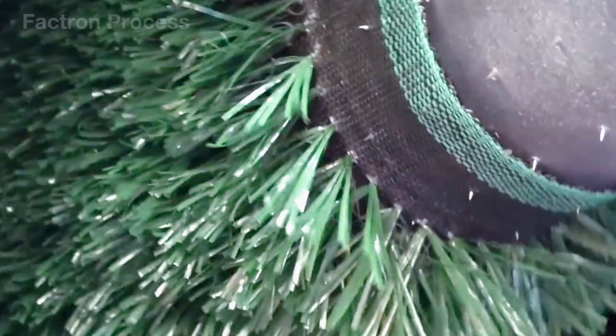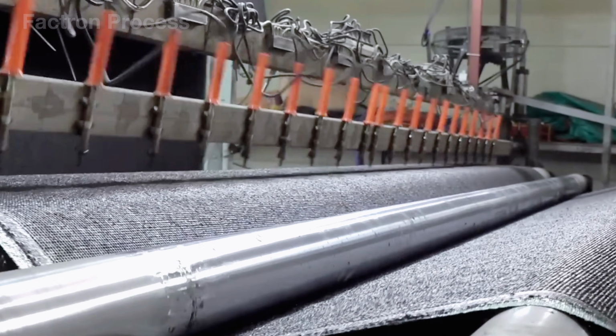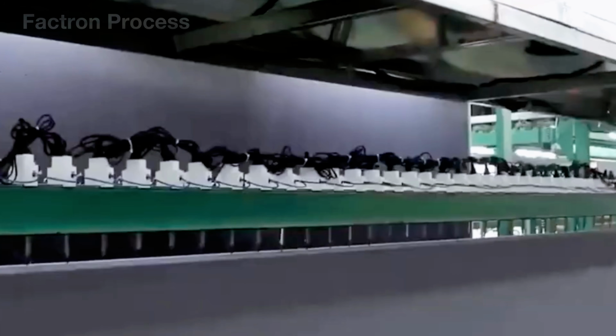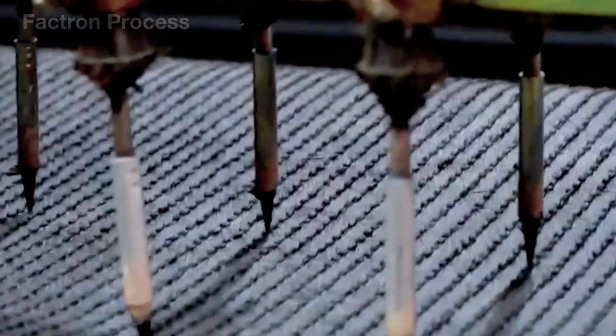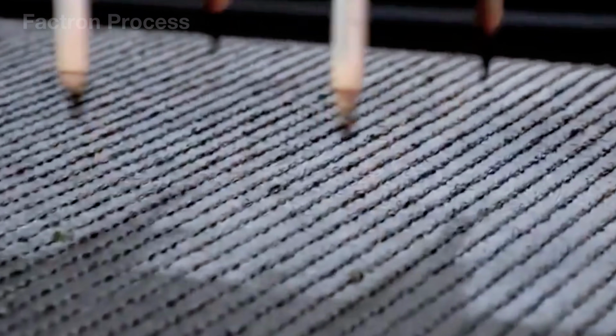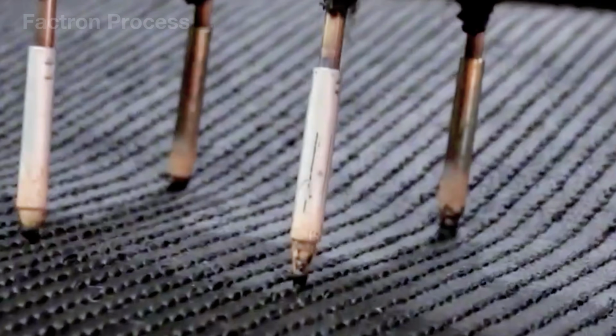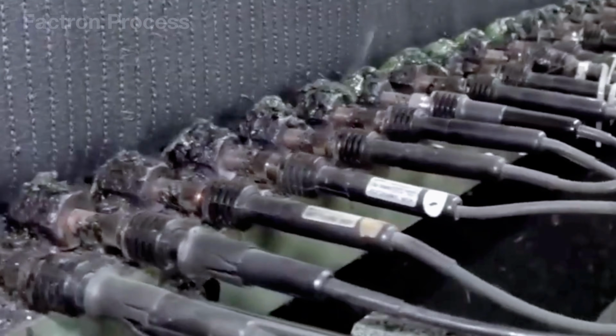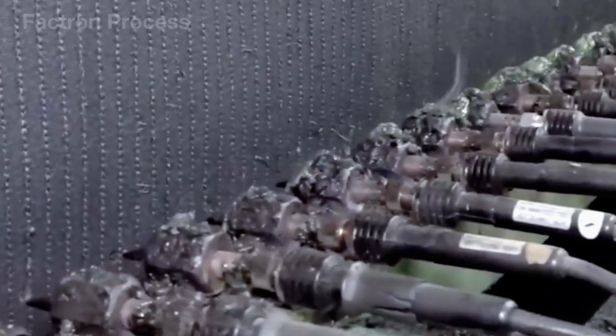Too few holes slow down drainage, but too many holes, or holes that are too large, can weaken the backing and reduce the carpet's stability. Each hole needs a clean edge without tearing the surrounding material. A small tear can expand under pulling force, thermal expansion and contraction, or long-term loading.